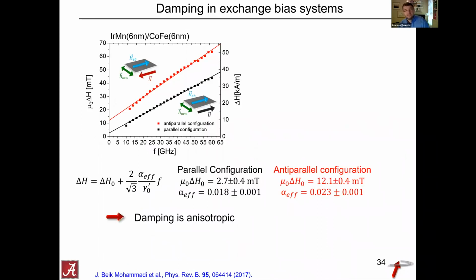So the bias was set in the film plane. If you go out of plane, it doesn't matter whether you go up or down. It's the same from the symmetry point of view. It's the same configuration. So you would get the same result whether you measure with a field up or down. So the obvious choice here would be to use a system where you can get the system bias perpendicular and then measure with a field up and down with respect to the film normal.